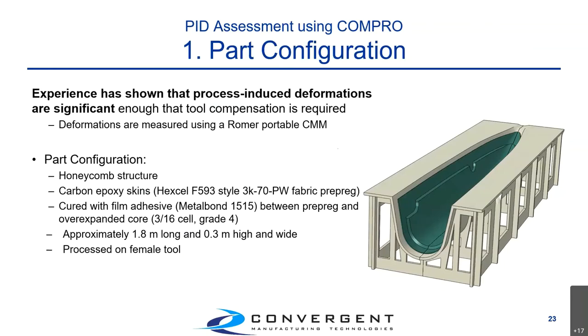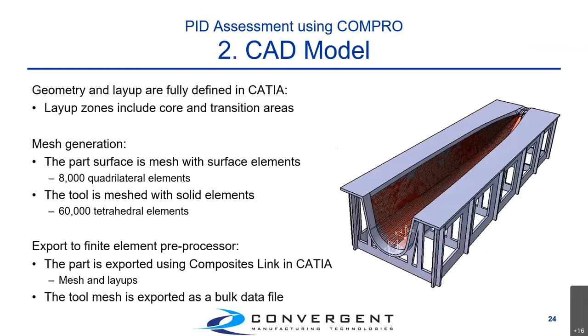In the analysis workflow, the first step is to define the part and process configuration. The part is a honeycomb structure with a honeycomb core and two composite carbon skins that merge at the edges. There are different layup zones, an adhesive between the core and skin in the sandwich areas, and the part is about 1.8 meters long and 30 centimeters wide, processed in a female tool. Using CATIA, we create the geometry of both part and tool — a solid tool and a surface for the part — with layup zones defined within that surface for export to Abaqus.